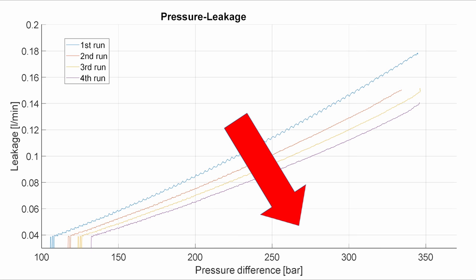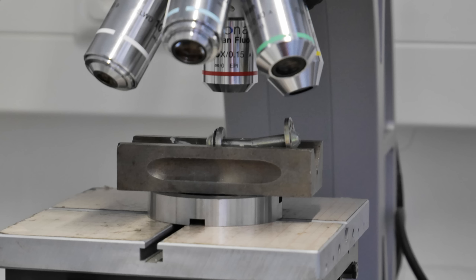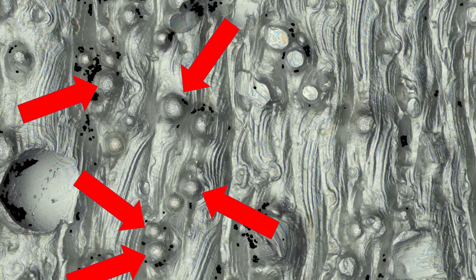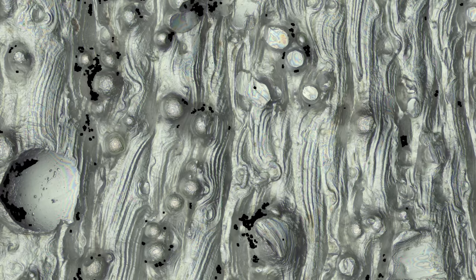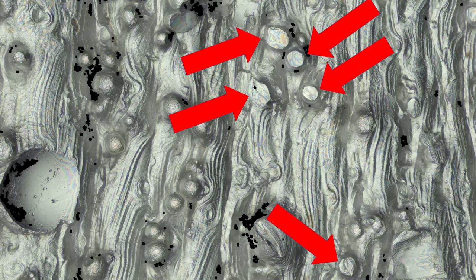However, what we did see was that with every test the check valve leaked less and less and less, indicating that the overpressurized Play-Doh sealing method that was planned would have worked if we would have had the time and the opportunity to test this. Inspecting the sealing surfaces under a very expensive but very cool microscope that can make 3D pictures, we can see the effects that we were going for. The welding bubbles that are typical for SLM 3D printing were starting to flatten out under the pressure and thereby creating a better sealing surface.